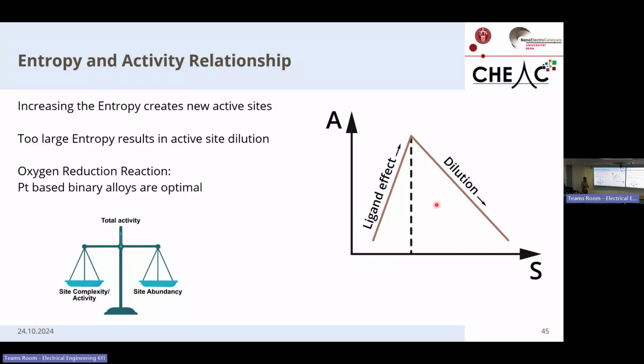So this picture of high entropy alloy catalyst now allows us to also get a qualitative relationship between the entropy and the activity. So the entropy is a measure for the degree of alloying. As we are making an alloy, we introduce ligands, and these result in an increase in activity. But at some point, we reach the optimal ratio between the site abundancy and its activity. And if we continue to increase our entropy, we start to dilute the number of these active sites. So we end up with a worse catalyst. And in case of the oxygen reduction reaction, this optimum can be found at around a binary catalyst.